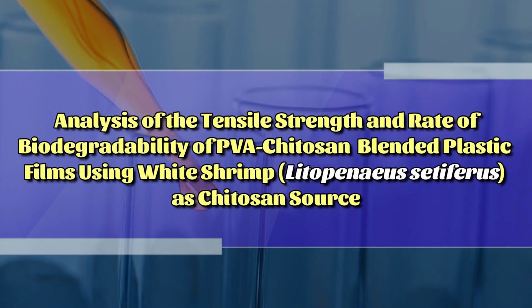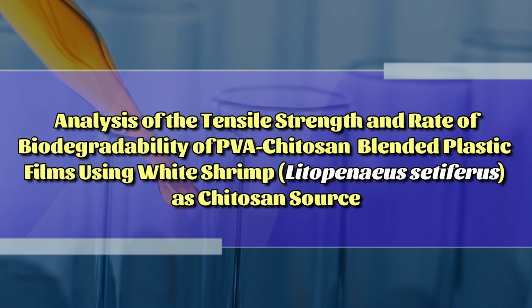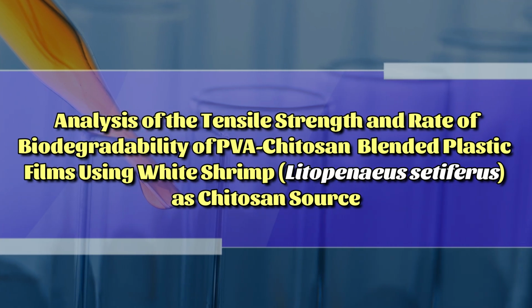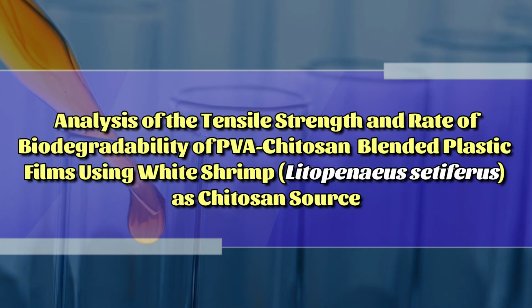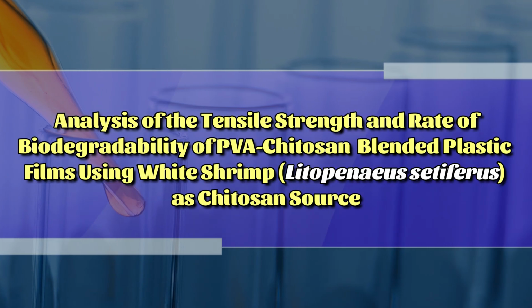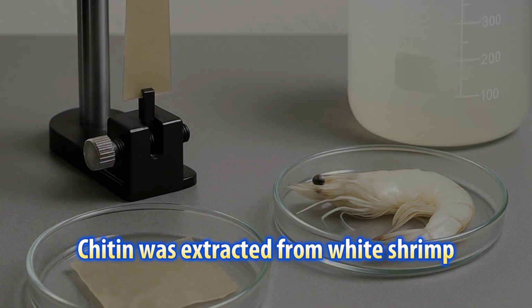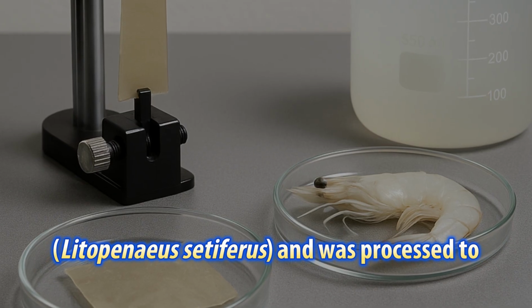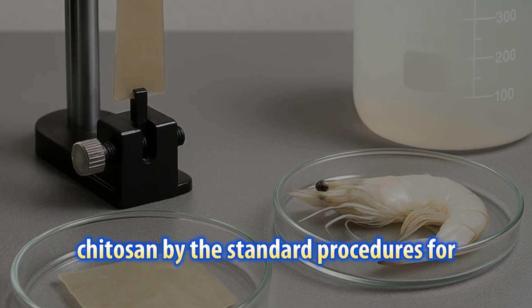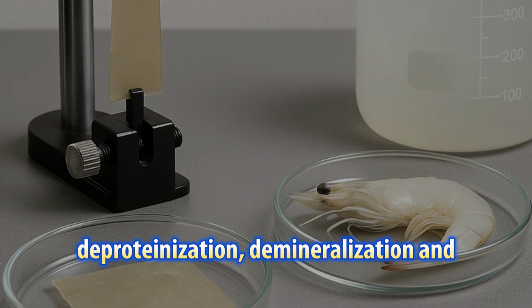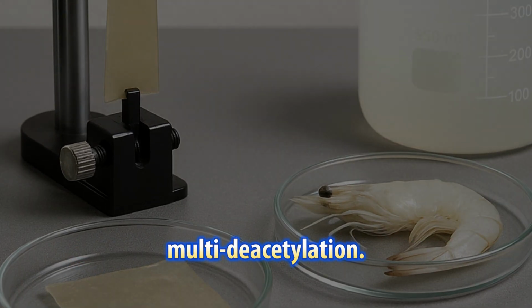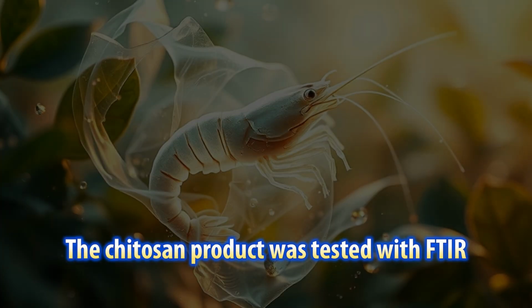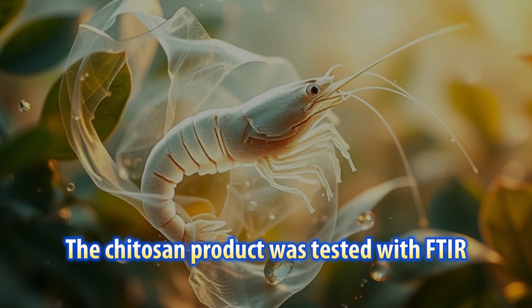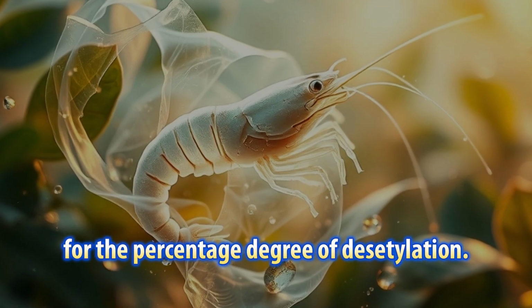Analysis of the tensile strength and rate of biodegradability of PVA chitosan blended plastic films using white shrimp Litopenaeus setiferus as chitosan source. Chitin was extracted from white shrimps Litopenaeus setiferus and was processed to chitosan by the standard procedures for deproteinization, demineralization and deacetylation. The chitosan product was tested with FTIR for the percentage degree of deacetylation.